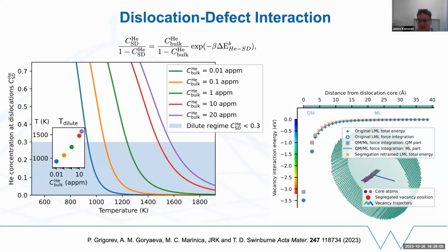And the final thing that I want to mention here that's quite nice is that we looked at interaction between vacancies and dislocation cores. So there we don't need additional chemistry. So in principle, the machine learning potential should be sufficient to capture the interaction. And actually that works out pretty well. So let me talk you through this. The original potential is shown in blue. So you can see it's matching with the reference results shown with the blue squares quite well here.